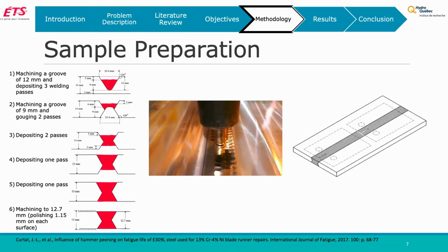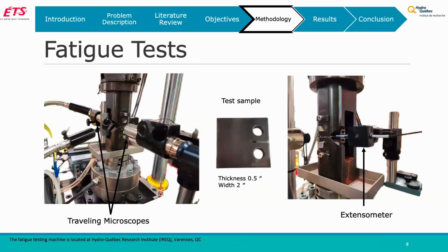And when we got our plate, we machined our sample in such a way that the crack propagates only through the filler metal. And the fatigue tests were performed on an Instron test bench with a test sample of the standard size of 1/2 an inch.